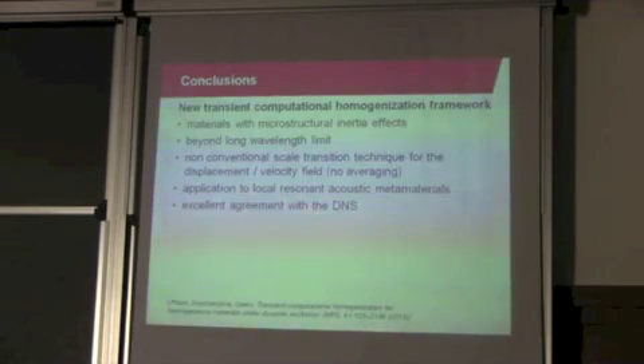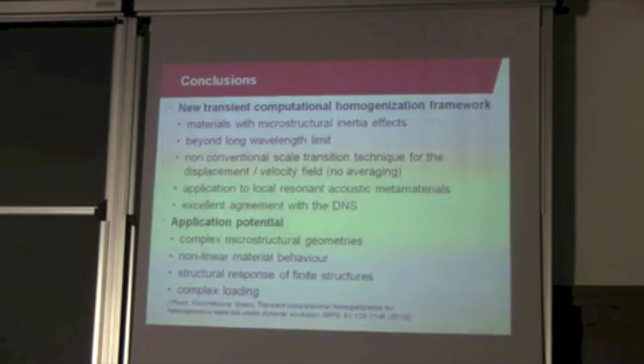And then we considered the application of this approach to the local resonant acoustic metamaterials, and we showed the excellent agreement with the direct numerical simulation, which is in this case believed to be the correct solution. And we think that there is a great potential for the application of this approach for complex microstructural geometries. So again, where geometries are finite with possibly complex boundary conditions, nonlinear material behavior, structural response of finite structures, where the structural response itself can start interacting with the local resonances, and arbitrary complex loading. So, thank you.